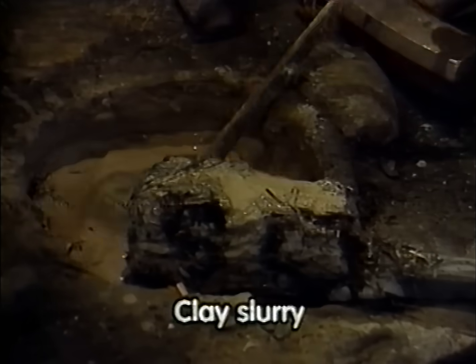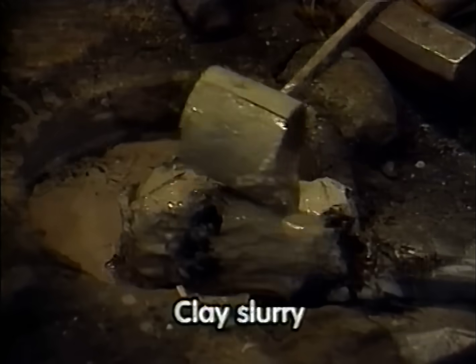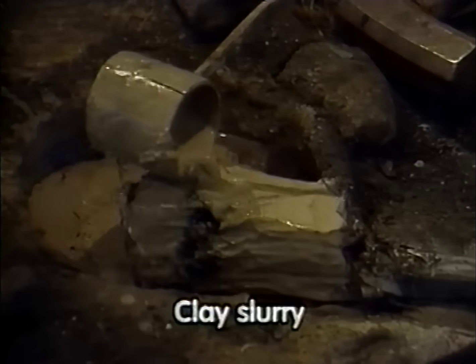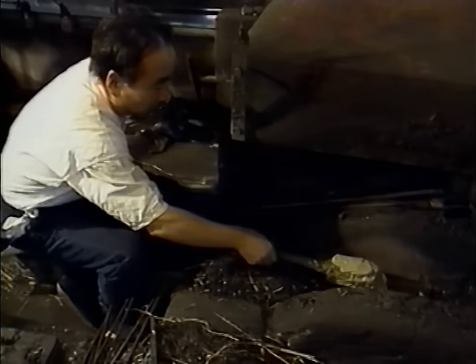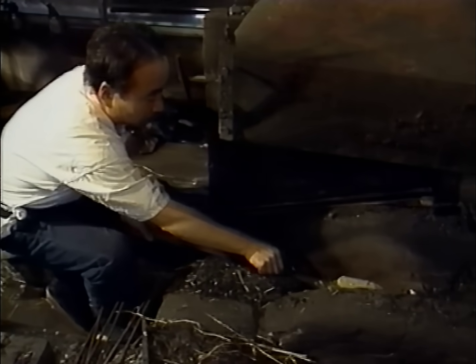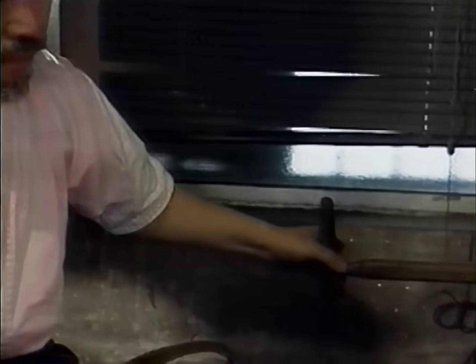Yoshindo now pours a clay and water mixture over the block. The clay and ash wrapping ensures that heat passes evenly through the block to its core. As the temperature of the block mostly rises from the outside in, this prevents carbon loss happening on the surface only. The result is a steel block which is uniform. The use of straw and the clay slurry is typically Japanese.